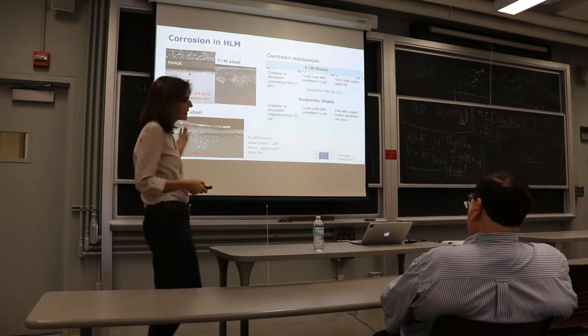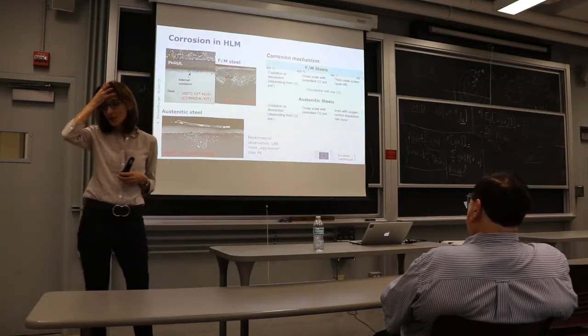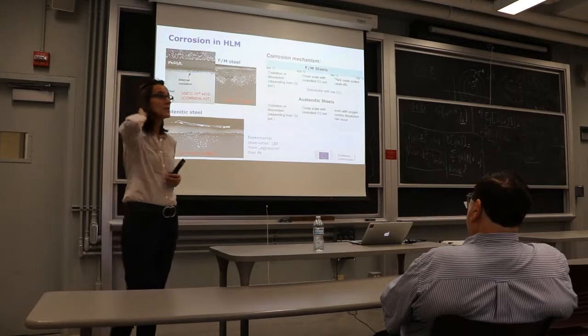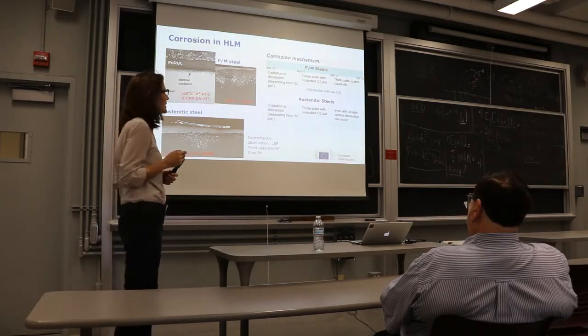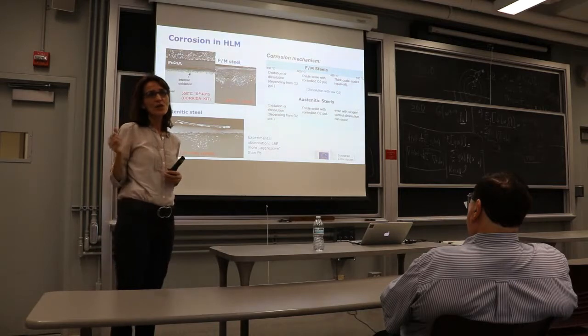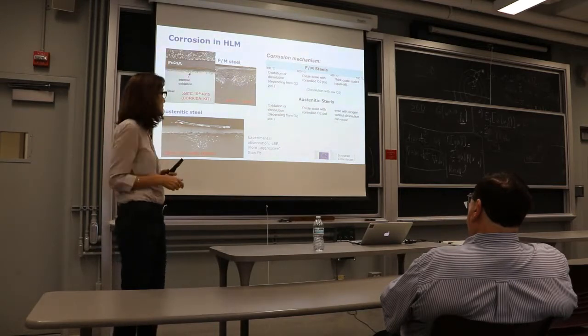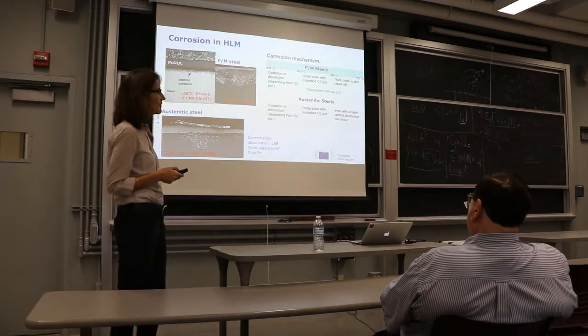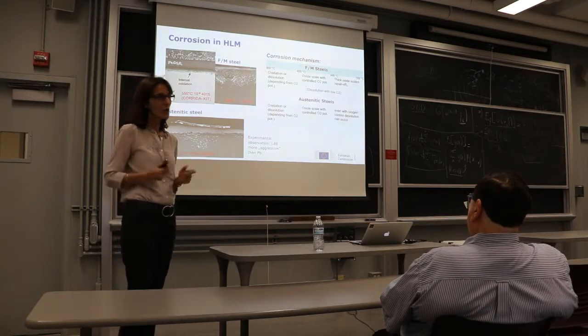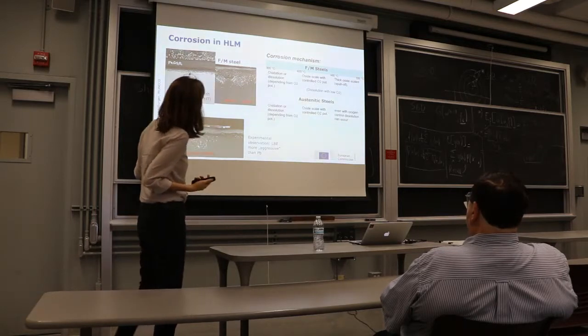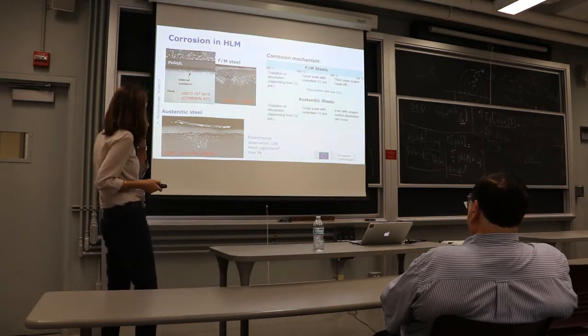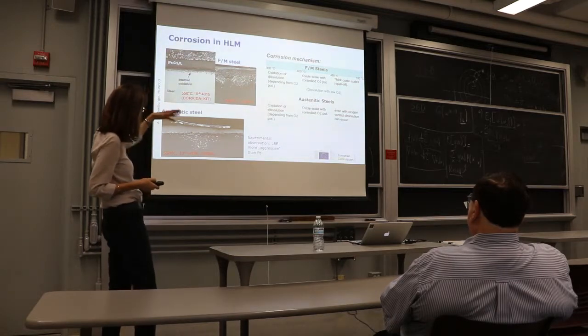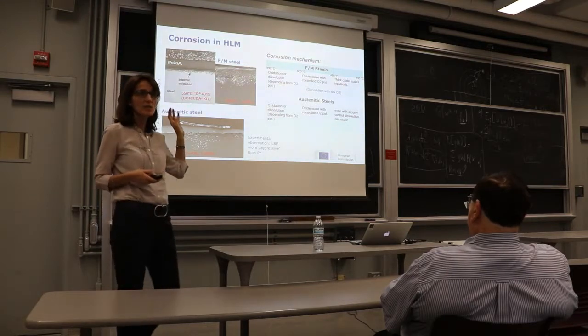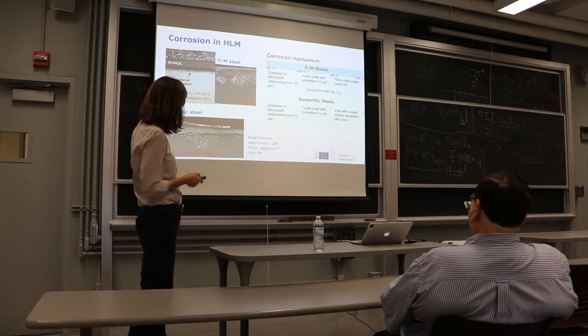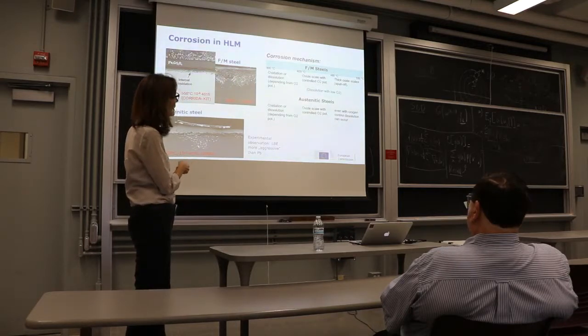And the other point, at least back to the origin that I said to you, that we were working on ADS system. This ADS system had as coolant the so-called heavy liquid metals. So these were either liquid lead or liquid lead bismuth. And these liquid metals are very, very corrosive. Again, a problem. But one should know the problem in order to see how to address the issue. We have seen that it is very corrosive both in the ferritic martensitic steel and in the austenitic steel. The type of corrosion mechanism that have been observed were the oxidation, but also the steel element dissolution.